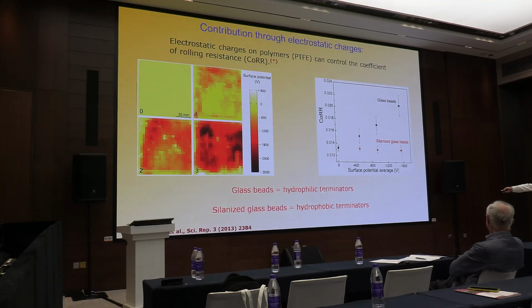Here the dipole is high enough to interact, and in the case of the silanized ones, you don't have a dipole, the dielectric dipole at the surface, for a strong interaction with the charges. This is the explanation from this author to conclude the article. And in principle, it's very good, this is a chemical approach, but with a physical point of view.